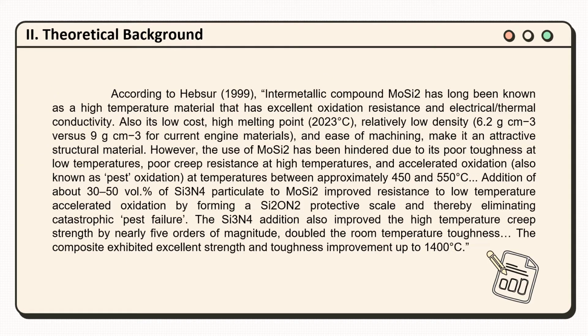According to Hebsur, intermetallic compound molybdenum silicide has long been known as a high temperature material that has excellent oxidation resistance and electrical or thermal conductivity. Also, its low cost, high melting point, relatively low density, and ease of machining make it an attractive structural material. However, the use of molybdenum silicide has been hindered due to its poor toughness at low temperatures, poor creep resistance at high temperatures, and accelerated oxidation at temperatures between approximately 450 to 550 degrees Celsius.